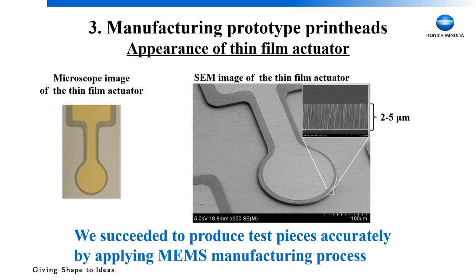This inset figure shows the cross-section of the thin film actuator. The thickness depends on the jetting properties, and for high viscosity ink, we need from 2 to 5 micrometers to generate high pushing power. As shown in this figure, we succeeded in producing test pieces accurately by applying the MEMS manufacturing process.